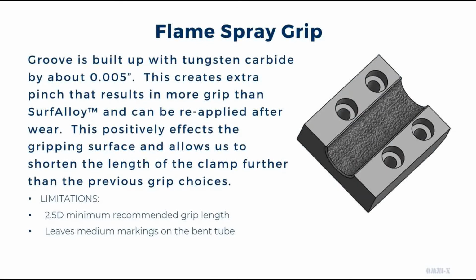Flame spray is a buildup of tungsten carbide by about 5/1000ths of an inch, creating extra pinch and more grip than Surfalloy. It can also be reapplied after wear. The more aggressive grip surface allows us to shorten the length further than the previous choices. Now, 2.5D is a minimum recommended grip length, and the medium markings will be more pronounced than that of Surfalloy.